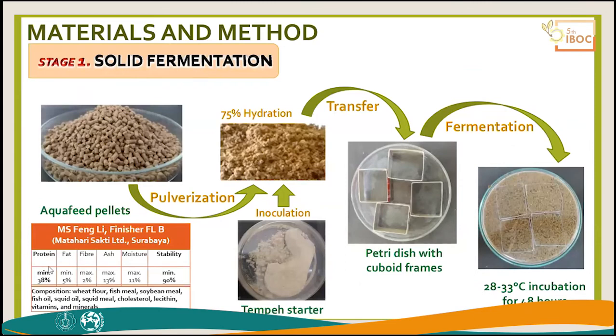So we use commercial sinking feed. We didn't formulate our own feed because our concern is not the nutrition but the physical properties of the fish feed. We got a sinking feed which is normally for shrimps. What we did is we pulverize it using a blender, and then we mix it with water to have about 75% hydration or moisture, and then we mix with tempeh starter or tempeh inoculum, which we purchased locally near our lab.